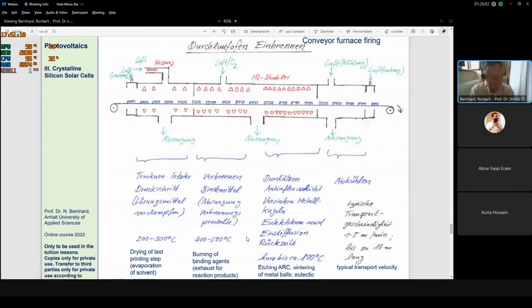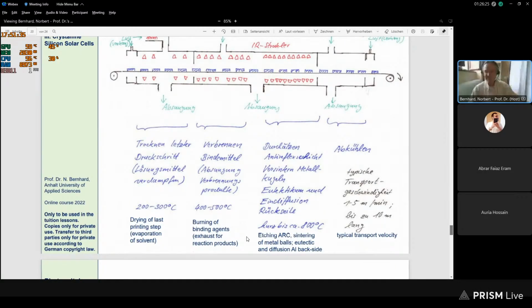And at the same time, it makes this additional aluminum doping I mentioned, to create the so-called back surface field. And then the last step is it cools down. The typical transport velocity, okay, it was somehow lost here, but it's given as 1 to 5 meters per minute, and such a conveyor belt is up to 10 meters long. That means it's also quite a big piece of equipment, and this is the second most critical process after the PN junction formation.